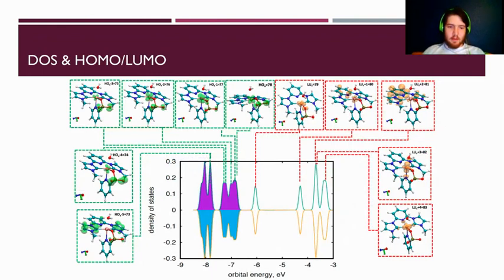So this is really the key of the entire presentation: a combined DOS diagram along with each of the orbitals that it represents. And what we can see here is that the LUMO is very, very close to the HOMO in comparison to the LUMO plus one. And this is obviously something that you want to see when you're working with a ligand, with a catalyst, as the ability to interchange between the conduction band and the valence band that you see with a very small band gap is very critical to being able to successfully make a usable catalyst, as without it, you will not be able to freely interconvert between the different forms of the intermediates of the reaction in an efficient manner. Next slide.